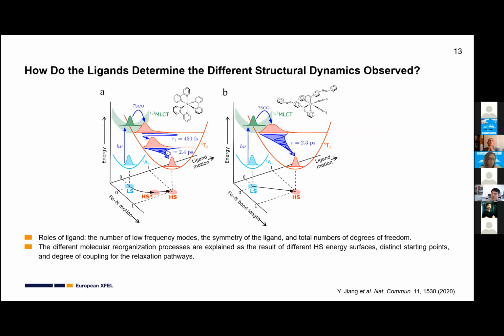Okay, so how do we understand the difference between BPY and AZA? For BPY, the photoexcitation is followed by spin transition, and the vibrationally hot high spin state has a narrow iron-nitrogen bond distribution, and it vibrationally cools inside the high spin state within 2.4 picoseconds. And for AZA, the ligand structure rearrangement is distributed during IVR, resulting in a broader distribution of structures that narrows over 2.3 picoseconds.